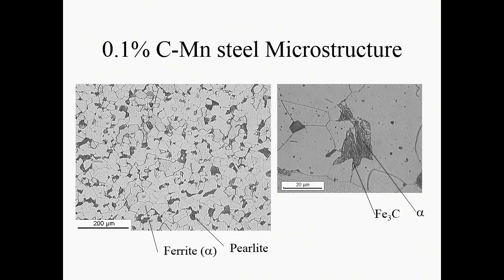So, the ductility and the toughness comes from the ferrite. The strength comes from the pearlite. That's why if we put more carbon in, we get more pearlite, more Fe3C in the structure, more strength. But this is good because the Fe3C is not as a big block of carbide. If it were a big block of carbide, it would crack very easily and steels will be brittle. And in fact, we know what big blocks of carbide do to steel because cast iron has big blocks of iron carbide, Fe3C in it, and if you make an iron casting and you hit it with a sledgehammer, you can quite easily fracture it into pieces. So we don't want big blocks of iron carbide.